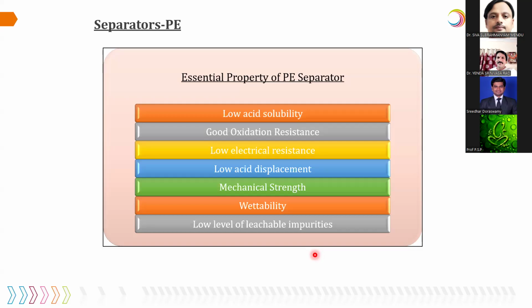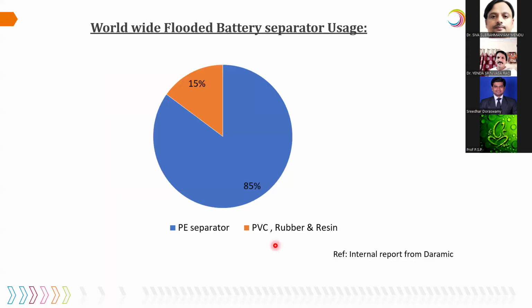So coming to the polyethylene separators, the essential properties for a polyethylene separator should be low acid solubility, good oxidation resistance, low electrical resistance, low acid displacement, mechanical strength, wettability, and impurities. Impurities should be low. Normally, in lead acid application, we talk the impurity should be at the ppm level. So the worldwide usage, we see 85% people are using the PE separator, and 15% other kinds of separators.